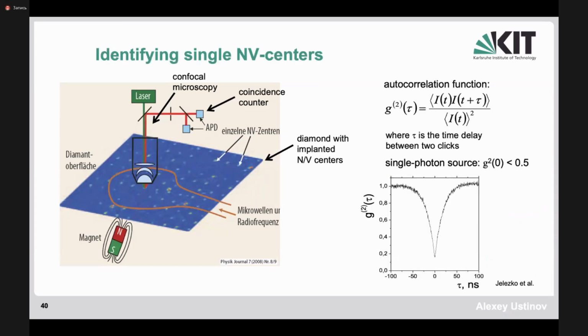So basically, how can we see that this is a single photon source? We need to measure the autocorrelation function. So basically, if we have now these 2 detectors, and we measure the signal from those 2 detectors as a function of delay between the measurements, then once the photon comes from the single photon source, it will either make the upper detector click or the bottom detector click. They can never click at the same time. And that means that the autocorrelation function, which we'll measure, will be depending on the time delay between the clicks. And if the delay is 0, then there will be no correlation at all. Basically, this means that there will be always one detector clicking or the other.